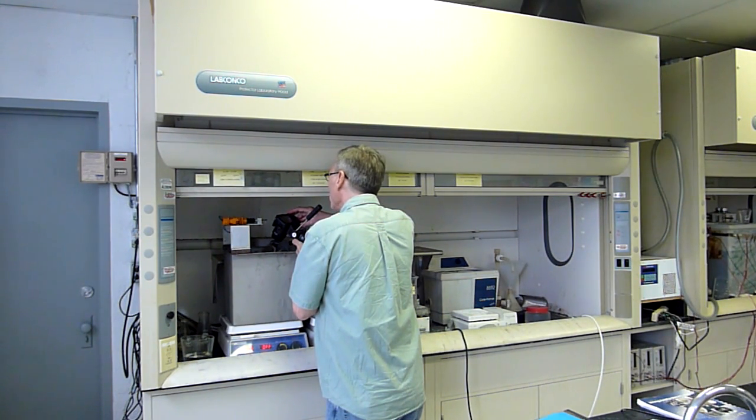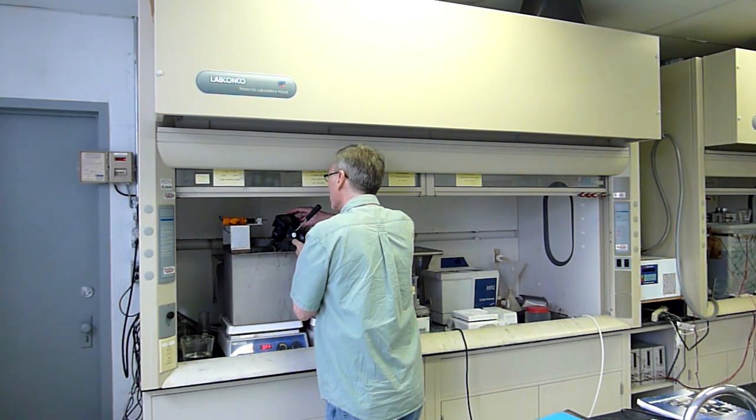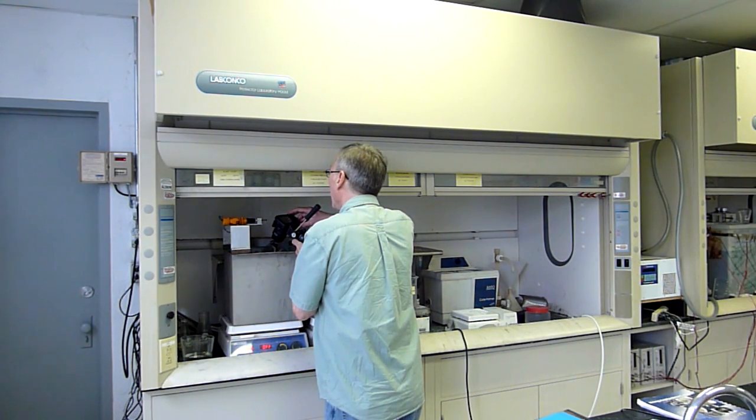We do have an issue that neither of our gold chemistries right now is really good at plating over solder. Dissimilar metals are always a problem because you're creating a galvanic cell where the dissimilar metals come together. And there's just a bit of an issue with plating solder on these components.